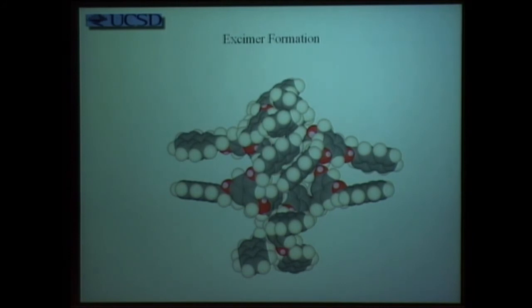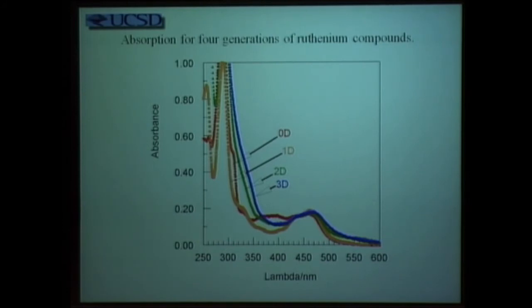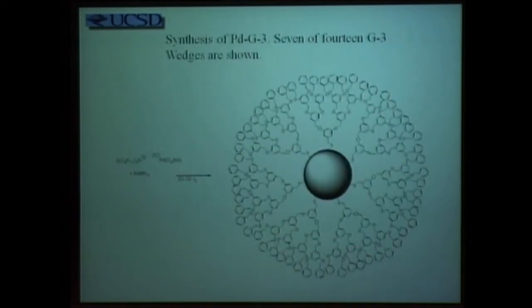You can see this also by looking at a spectrum with 0, 1, 2, 3 shows increasingly strong absorption in the visible region of the spectrum. And in particular, this, what's called plasmon band, corresponds very effectively to the kind of redox catalyst we've described earlier. Finally, let me show you one other catalyst. This is a palladium catalyst. Palladium is used for a number of reactions. But as you can see, like the one I showed you, the third generation, it has lots of room very near the surface. So small molecules can get in, react, and come out, whereas larger ones are blocked by the channels on the dendrimer. So what I hope you've seen here is the same kind of catalyst that we have looked at for absorption in photoelectrochemical cells also have unique chemical characteristics in terms of palladium.